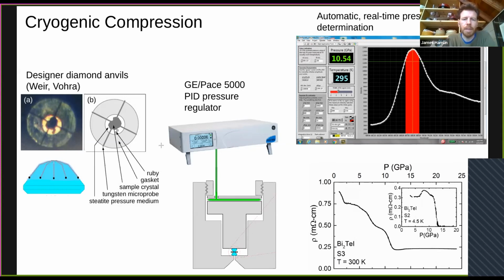So these modern nanofabrication, microfabrication techniques have a lot of potential to add new probes to high pressure measurements. We then use a standard membrane-driven diamond anvil cell. So this membrane is filled with helium gas, which means that as long as we keep the pressure below about 25 bars, we can adjust the force applied to the diamonds at any temperature down to low temperature.